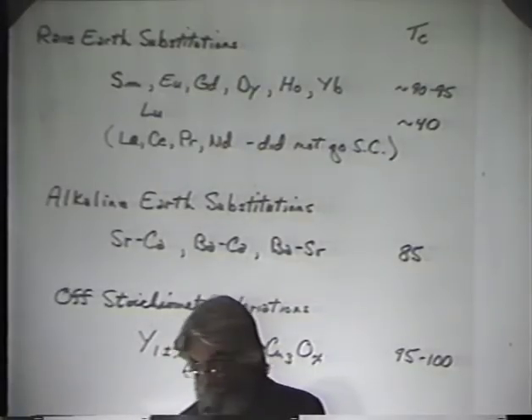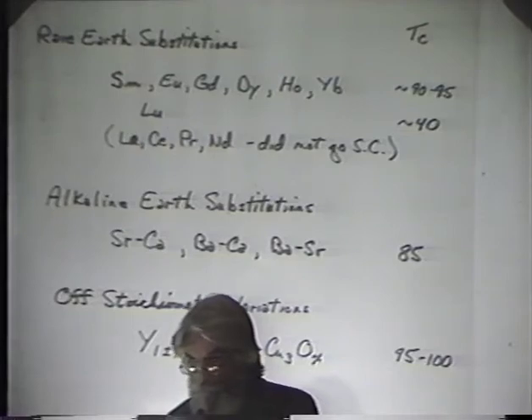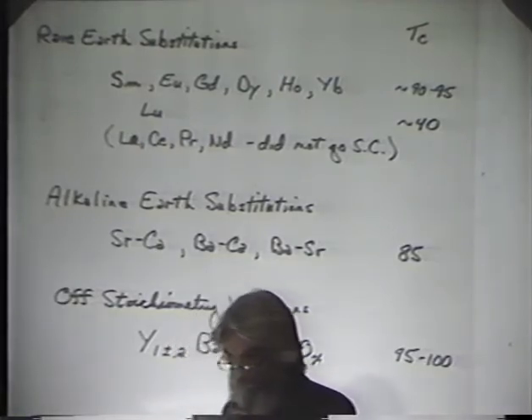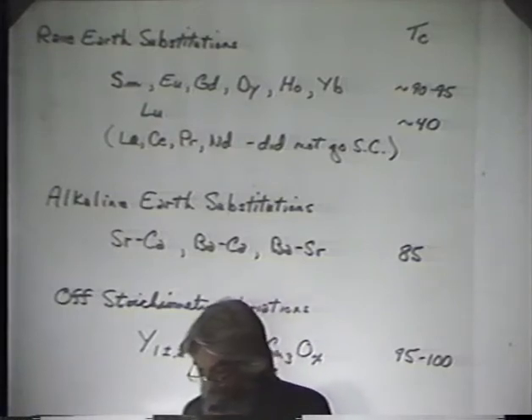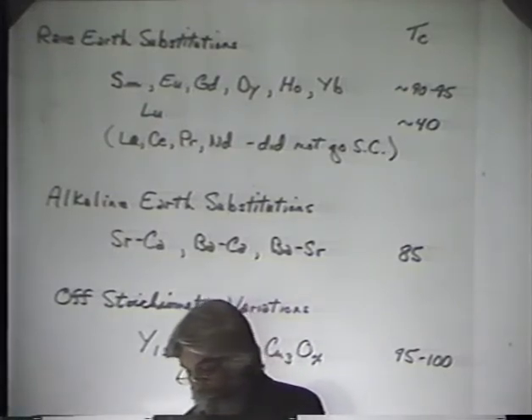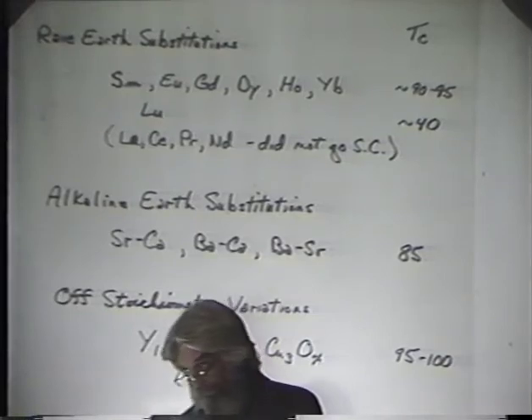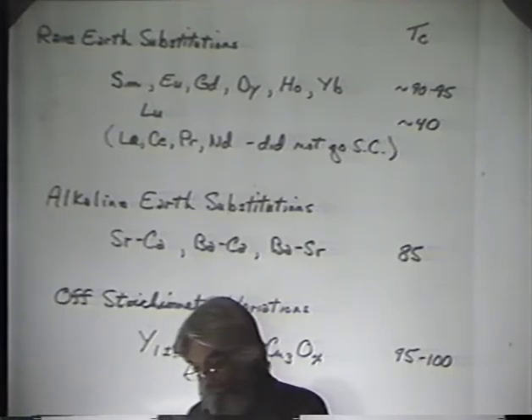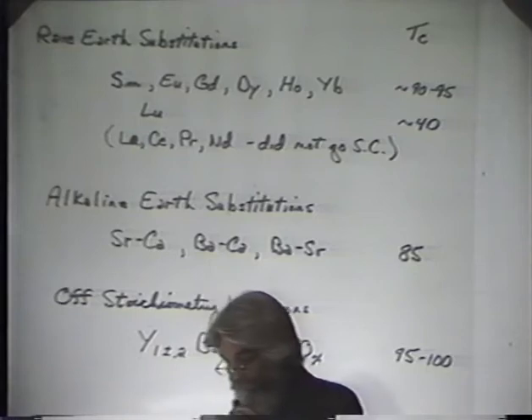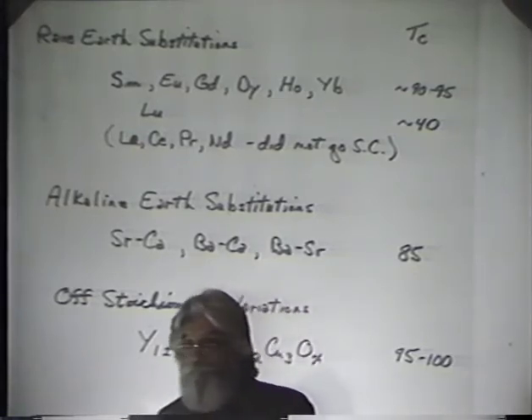We did a partial substitution of calcium for barium and strontium for barium. You might think there was phase separation perhaps, but the X-ray data was very, very clean, indicated single phase. But the clincher is when we put in 50-50 strontium, calcium. All three of these alkaline earth substitutions, both complete and partial, gave a transition temperature onset in the range of 85 degrees. Now, we did try calcium alone and strontium alone, and to date that hasn't worked for us. But it may be that we have to be more careful with the annealing. Don't know. Thank you.